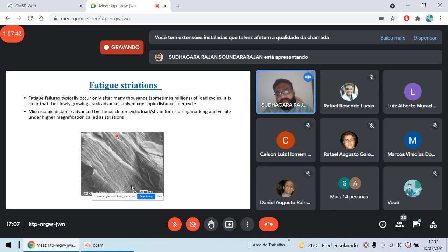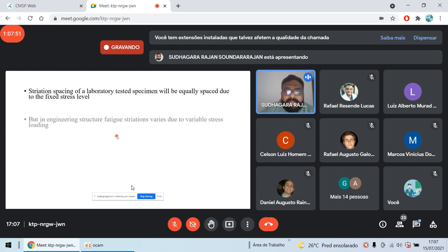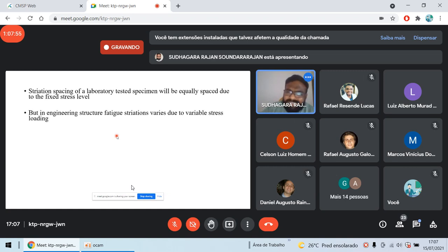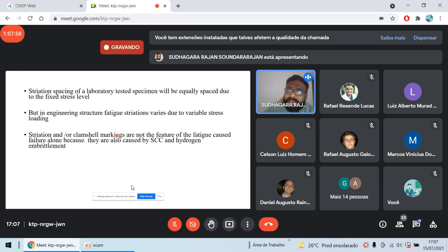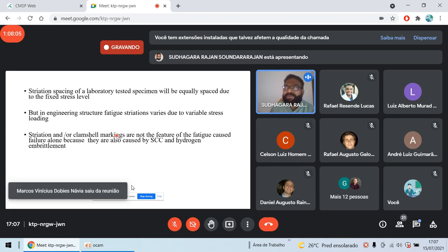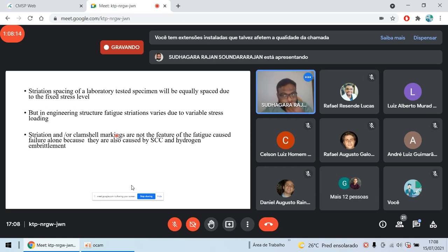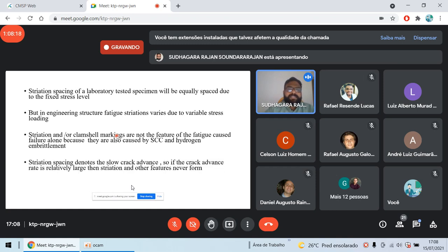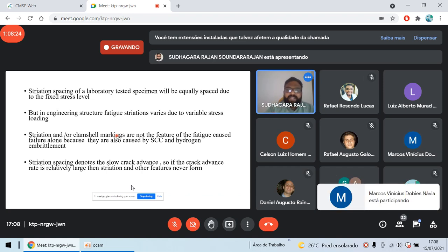The previous images are all normal photographs, but this one is an electron photograph, like SEM. The striation spacing in the laboratory will be equally spaced, because you are applying a constant amplitude. Obviously, it should be equally spaced. In a laboratory failed specimen, it may look very beautiful, but in normal failure, it won't look like that. In engineering structures, fatigue striations vary due to variable stress loading. Striations and clamshell markings are not features of fatigue failure alone. That is another important thing you have to note. They are also caused by stress corrosion cracking, hydrogen embrittlement, everything.